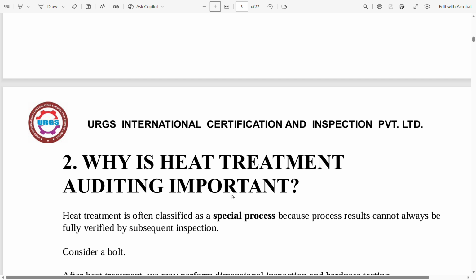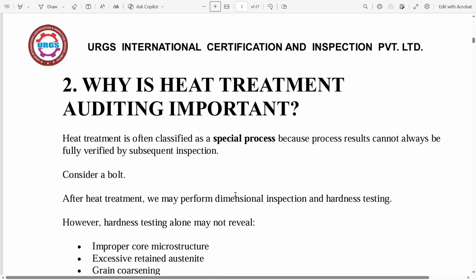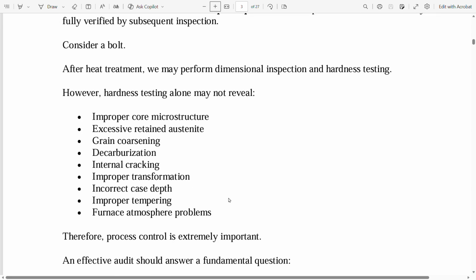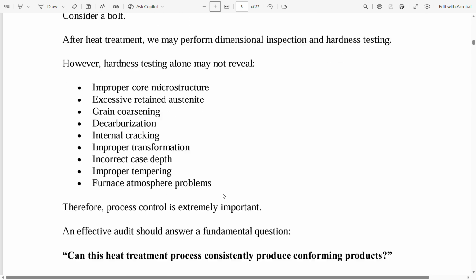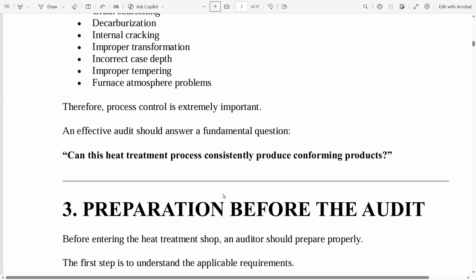Now, why is heat treatment auditing important? Heat treatment is often classified as a special process because process results cannot always be fully verified by subsequent inspection. Consider a bolt. After heat treatment, we may perform dimensional inspection and hardness testing. However, hardness testing alone may not reveal improper core microstructure, excessive retained austenite, grain coarsening, decarburization, internal cracking, improper transformation, incorrect case depth, improper tempering, furnace atmosphere problems. Therefore, process control is extremely important. An effective audit should answer a fundamental question: can this heat treatment process consistently produce conforming products?